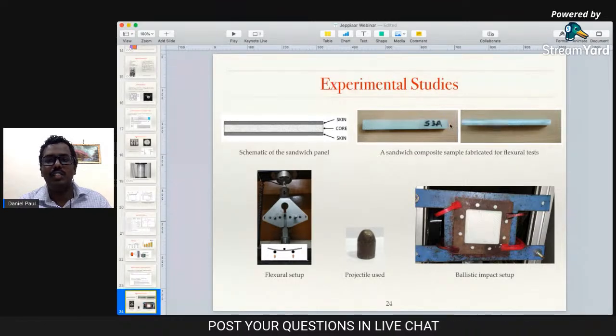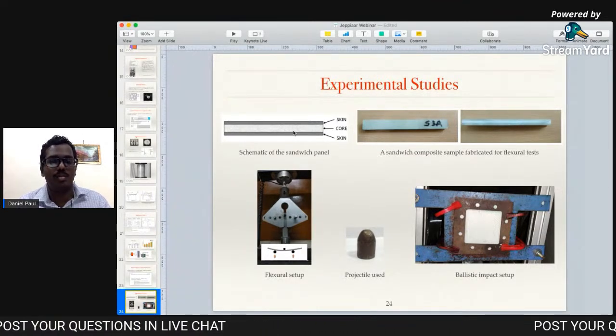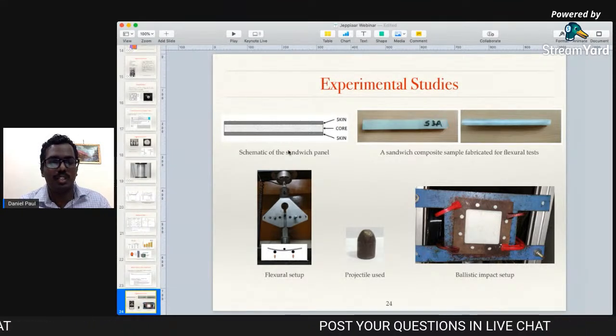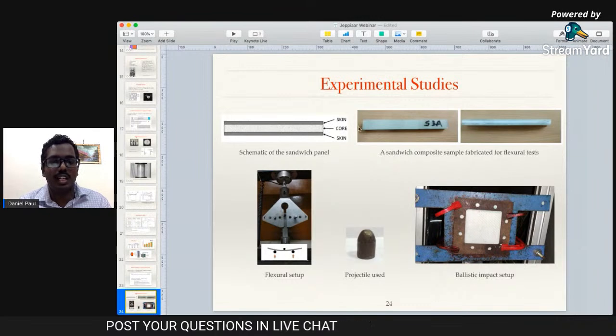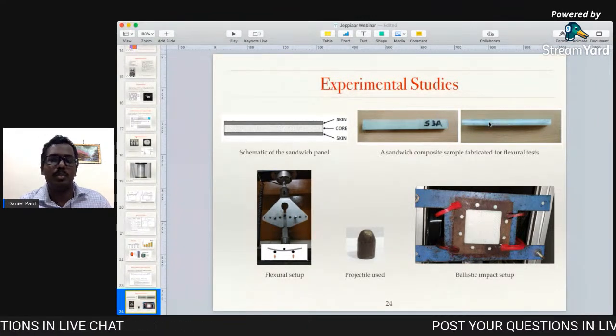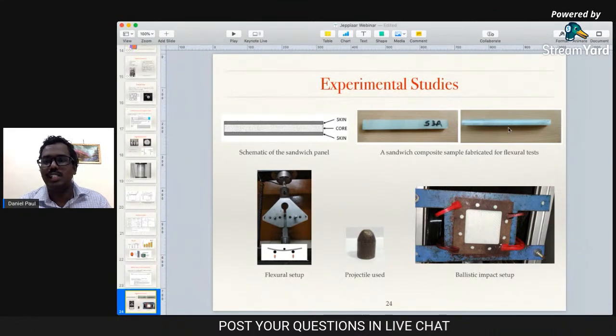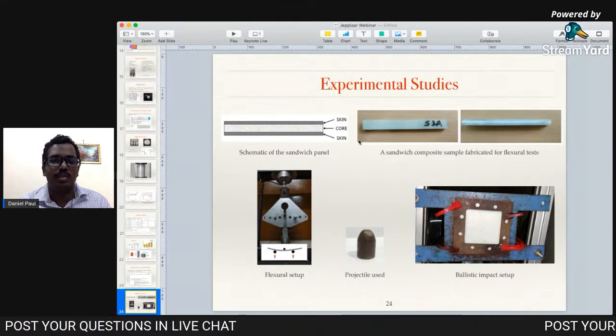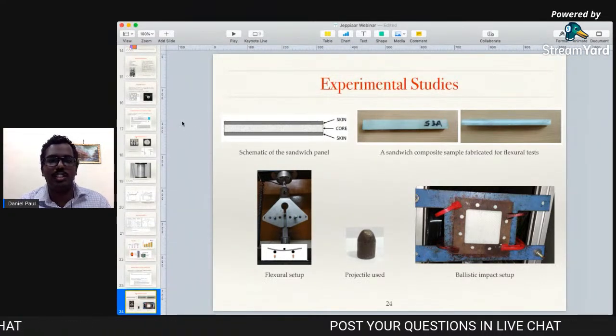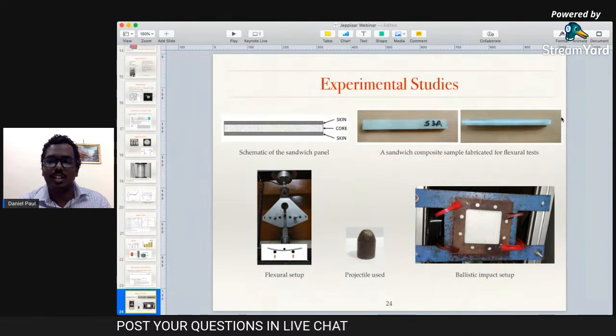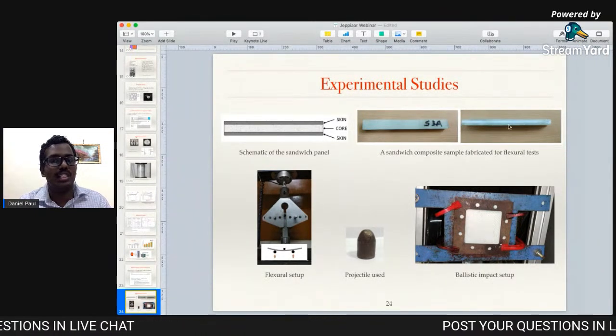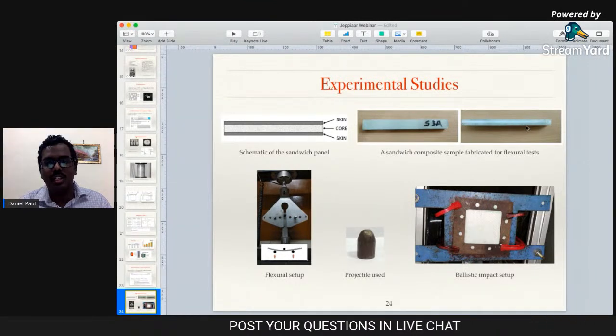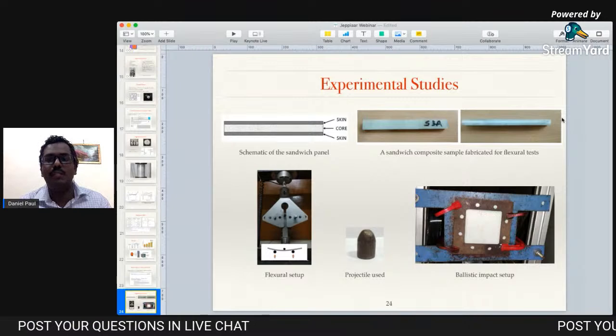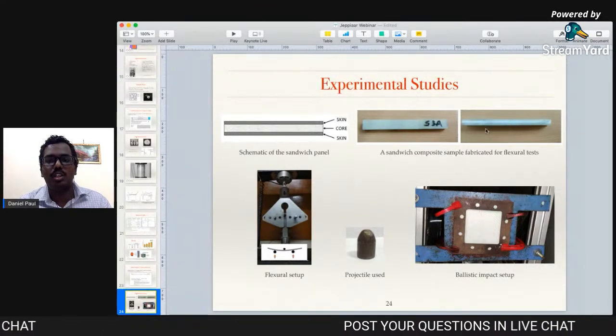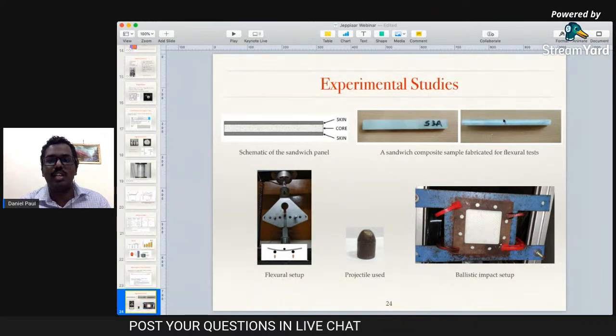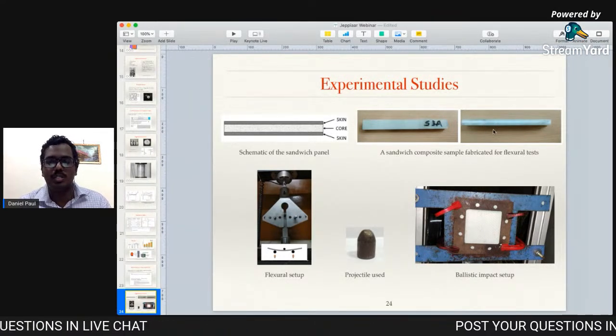In the manufacturing of this, in this case also we wanted to increase the energy absorption of this particular structure. In our case, both the core and the skin are composed of the same matrix, which is epoxy. This is a nice thing because we can co-cure it. It's not like we make the skin separately, the core separately, and then join them together using an adhesive. On the other hand, we make the bottom layer, wait for some time till it gels, make the core, and then before the core gels or cures completely, we make the top skin. So it's a co-cured method in which the entire composite cures at the same time, and so we were hoping to increase the energy absorption of this material.